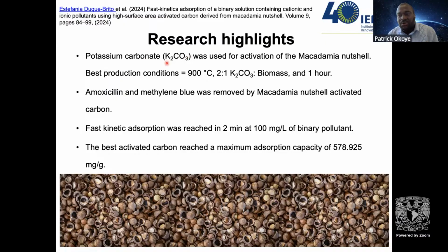We use K2CO3, potassium carbonate, which is a far more environmentally friendly material compared to zinc chloride. Under optimal conditions of 900 degrees Celsius, 2:1 potassium carbonate to biomass, and 1 hour, we obtained a superior material that gave us a maximum adsorption capacity of 578.9 milligram per gram. This adsorption capacity is a combined adsorption capacity of the combined pollutants, because we combine these two pollutants in one system and try to remove both of them.